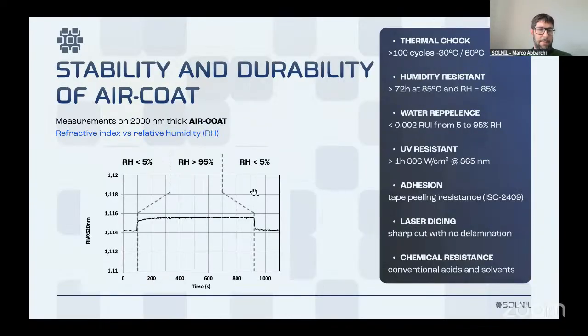Here I show some example of tests that have been done. For example, on 2 micrometer thick air coat, we measure the refractive index as a function of humidity. So from 5 to 95% humidity, the refractive index changes from 1.114 to 1.115 or a bit more, meaning that this material is water repellent.